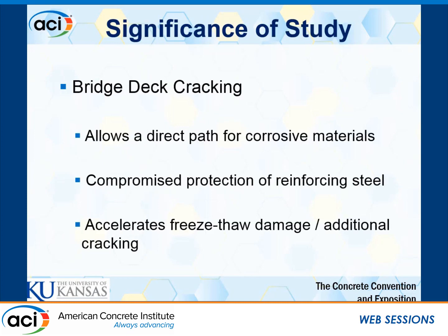The significance of bridge deck cracking from a corrosion standpoint is that those cracks can allow for ingress of corrosive materials and chlorides, which, if you have uncoated bars, can really compromise your corrosion protection, initiate early corrosion, and accelerate the damage due to corrosion losses and spalling of concrete and so on. And from a cracking and durability standpoint, those cracks can accelerate durability issues such as freeze-thaw.